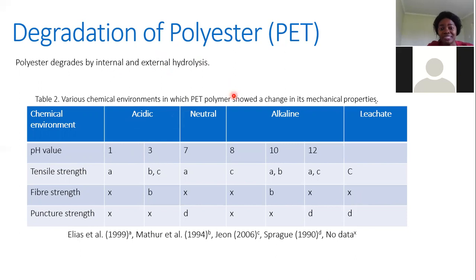And the most dangerous or the most severe hydrolysis takes place in the alkaline environment because it changes the structure. It erodes the surface of the polyester, and that's where degradation takes place faster. So as reported by several authors, we found out that polyester, when subjected to various chemical environments, there's a change in its mechanical properties, such as the tensile strength, the fiber strength, and even the puncture strength.